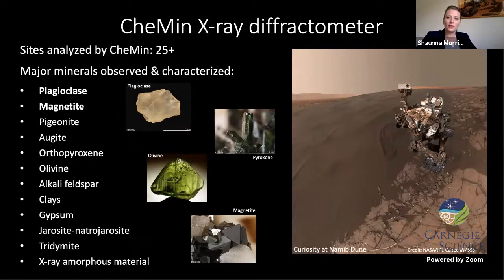And then we've often found minerals associated with weathering and alteration, especially clay minerals. We found a range of clay minerals that form in different environments. Some were likely more habitable than others, but what they all have in common is long-standing water on the surface or near subsurface. Likewise, we've observed gypsum and other associated calcium sulfates that provide further evidence of long-standing bodies of water. Lastly, we've occasionally found jarosite, which is a hydrous sulfate, and it's commonly associated with acidic conditions. So there were likely areas and time periods during Gale Crater's long history that environments had a lower than neutral or acidic pH. Then lastly, I'll mention two puzzling phases.